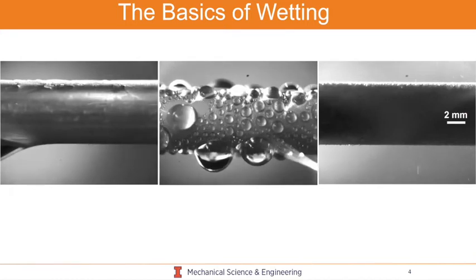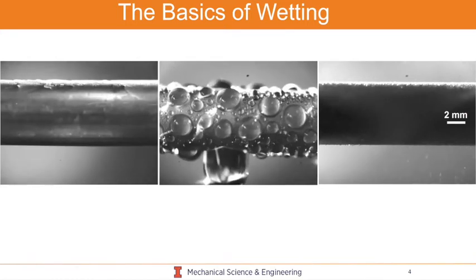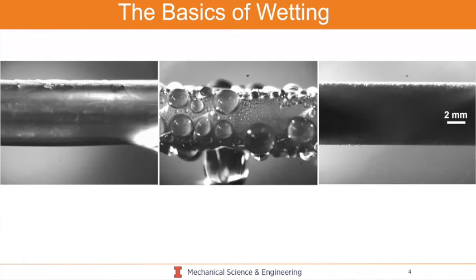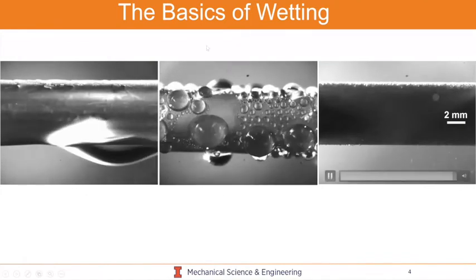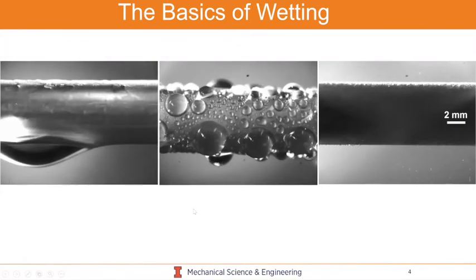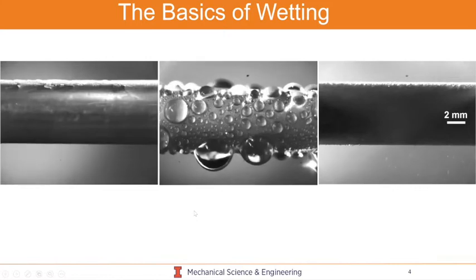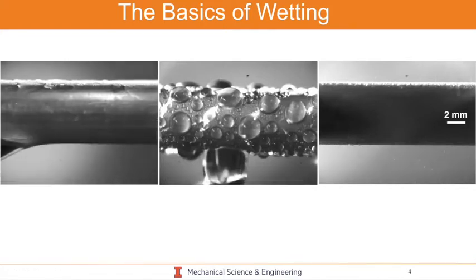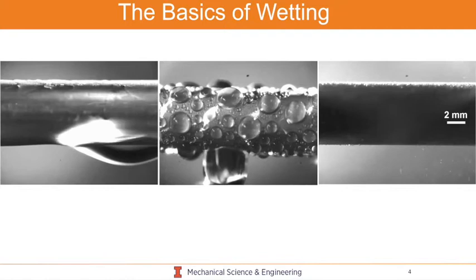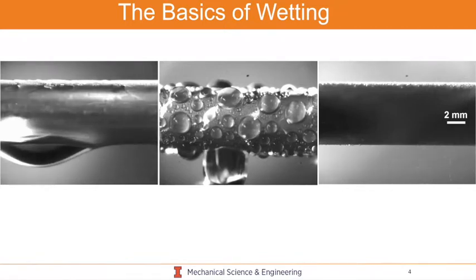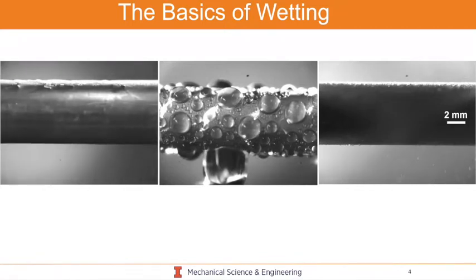You could actually transition from these two drastically different modes of condensation, where this middle mode here gives you a 10 times improvement in heat transfer. So you're getting a 1,000% improvement in performance for adding one molecule layer onto your surface. And that's essentially the power of the interface, and hence why we really focus on it.